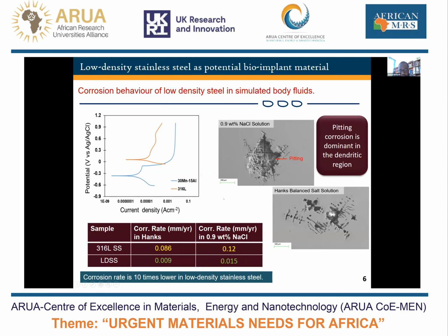But we found something quite interesting. We saw that in the low density stainless steel, there is a lot of pitting, because the pitting occurs in the dendritic region. So you have the carbides and the matrix forming the dendrites, and I think the chloride ions attack the interface between the carbides and the matrix. The matrix could be a mixture of ferrite and austenite, depending on the amount of manganese, aluminum and carbon that you had. So we saw this, and we thought if we subject this to thermomechanical processing, we can get rid of the pitting. But how that affects corrosion rate, we didn't know.